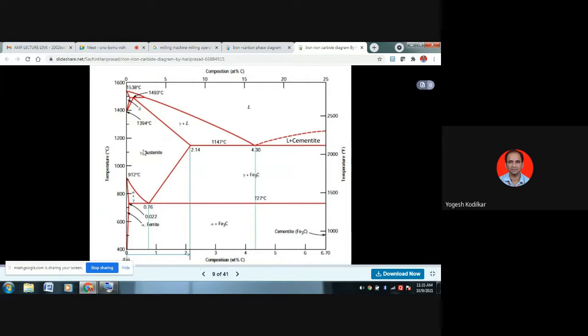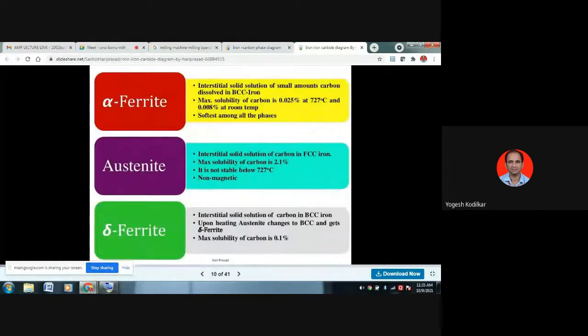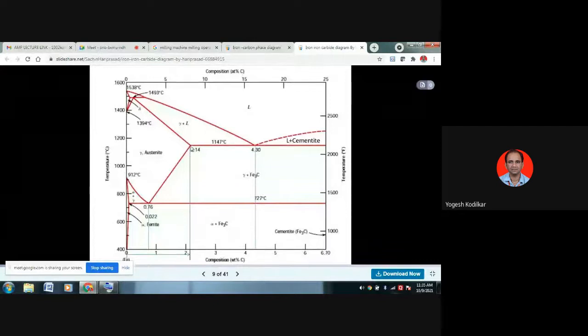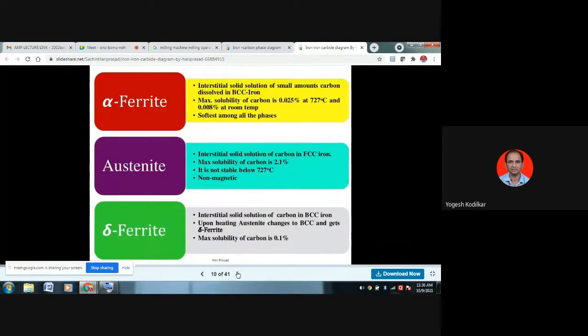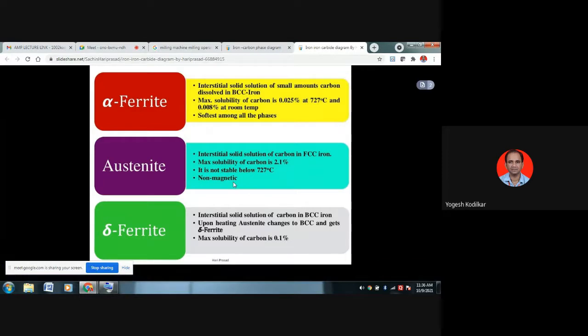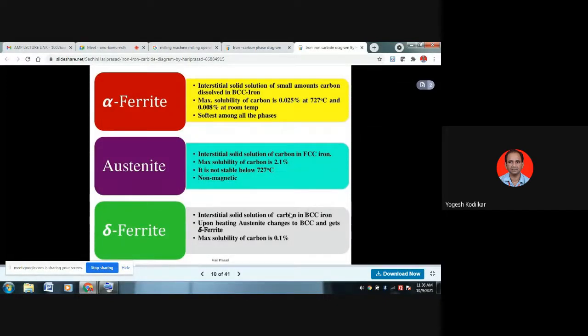So that gamma austenite phase has a carbon solubility of 2.1%, that is 2.14%. It is an interstitial solid solution of carbon having FCC iron, and it is not stable below 727, and it is basically non-magnetic. Austenite, that gamma iron, is the non-magnetic phase, and when the temperature is increased, it is called the delta phase, delta iron or delta ferrite. This is again an interstitial solid solution of carbon. Again FCC is converted into BCC, so an interstitial solid solution of carbon in BCC iron.